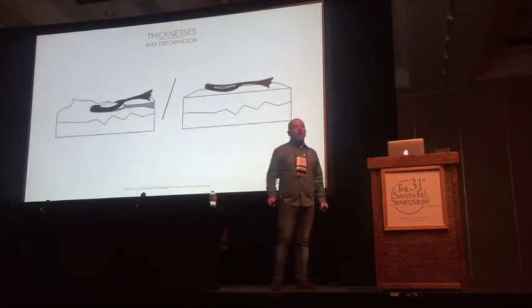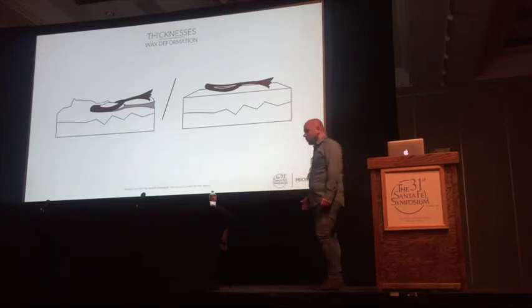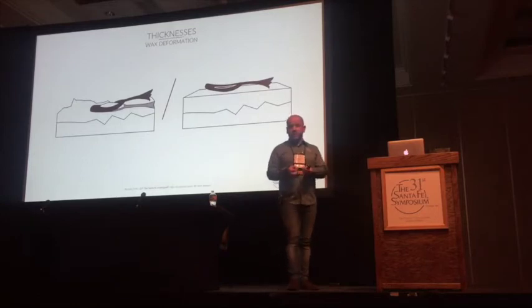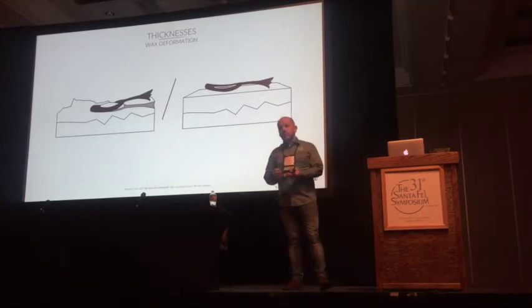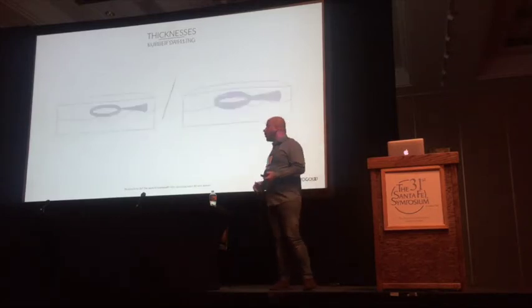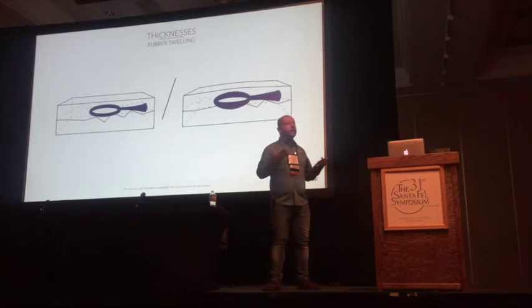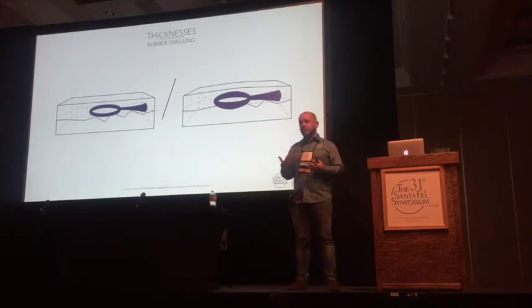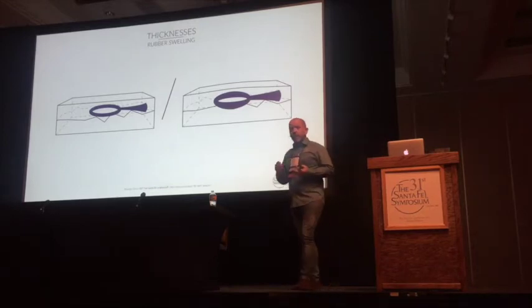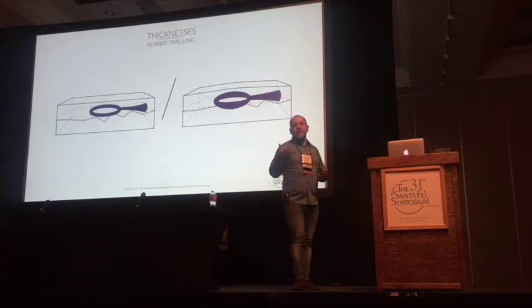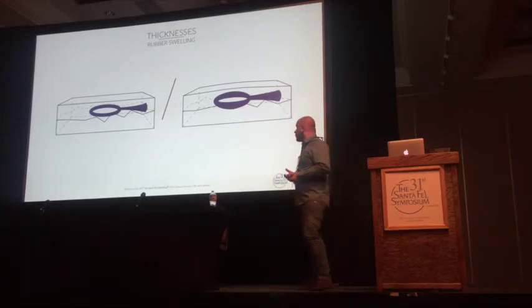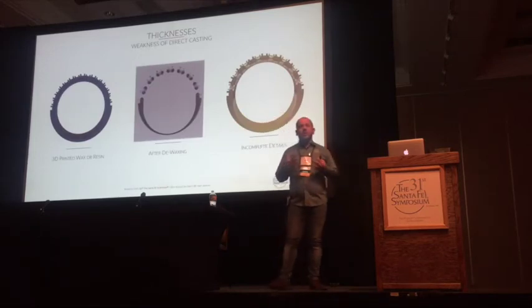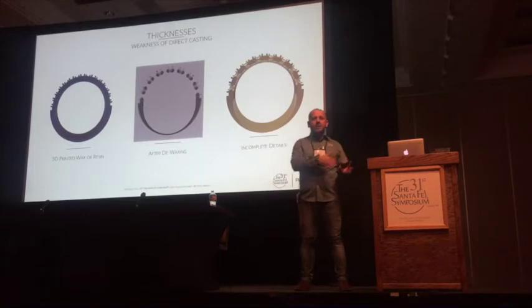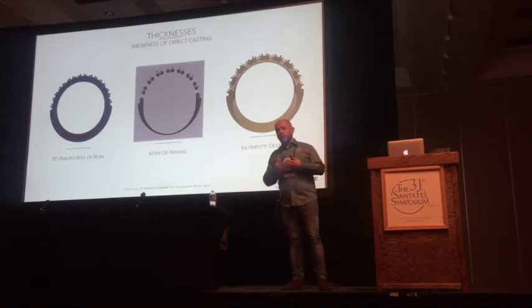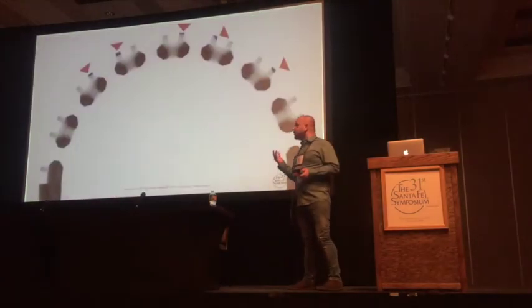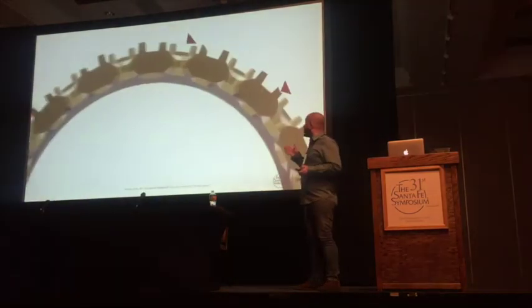That is one of the issues about 3D metal printing. In the case of traditional casting, it's very common, if you have a teeny part, when you extract it from the rubber mold, that the deformation is always behind the corner. Or if you have to inject something very thin, then it's very easy to increase the pressure too much and you have rubber swelling, and the size of the wax is no longer the one that you were looking for. Or in the case of direct casting, you have a problem that the polymer used, whether it's wax or resin, cannot be really removed. And sometimes you have some residual which affects the form filling capabilities. So you have some missing metal.